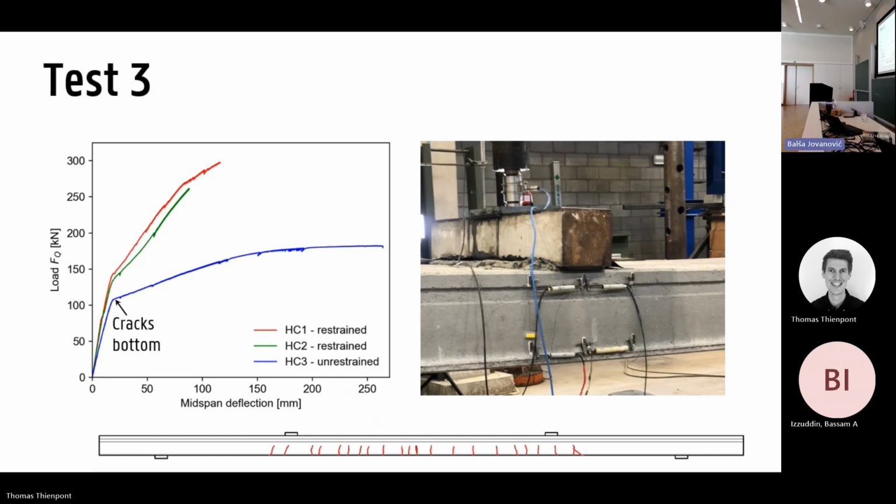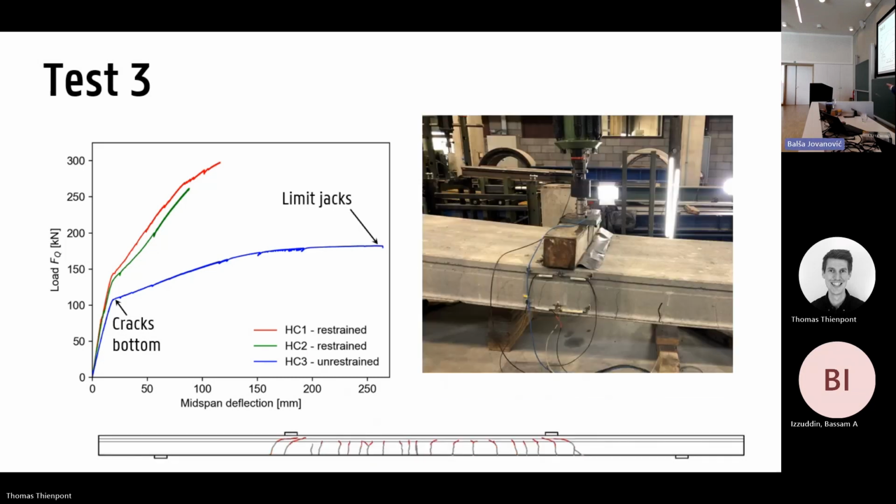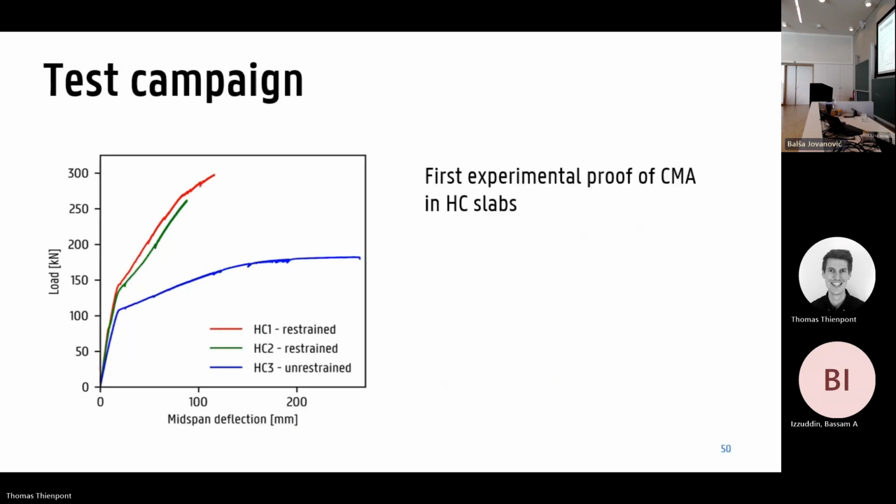Okay, so again, if we break down the curve, this one is a bit less complex. Basically, we reached the cracking load, and after that, the angle of the curve was much flatter, and we reached the plateau. And then we reached the limit of the jacks. And again, you see the cracking pattern at the bottom once again.